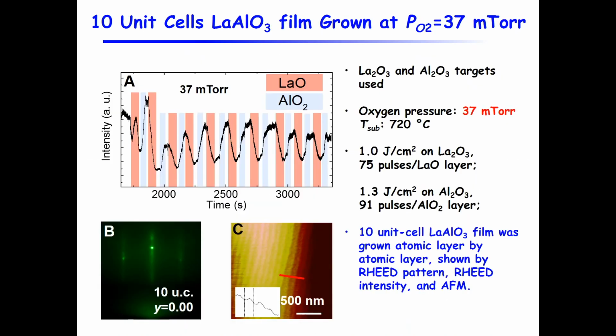So, our work. We use the technique that I introduced to you, this atomic layer-by-layer laser MBE. And all the work that I'm going to present is on 10 unit cells of lanthanum aluminate. And we grow them at 37 millitorr. There has never been a report that can grow these materials layer by layer and still be conducting at this kind of pressure. As I said earlier, the highest pressure reported is 10 millitorr.